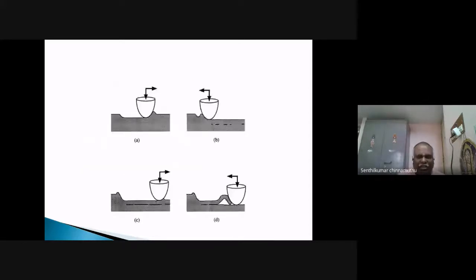See, you might have seen that figure. First, the load is applied and the pin is moved on the surface. First, the material is plastically deformed, and figure B shows the material plastically deformed and the crack nucleated under the surface. Again the crack is propagated in C, and in figure D, it is removed in the form of flakes or thin sheets. This is called delamination wear.